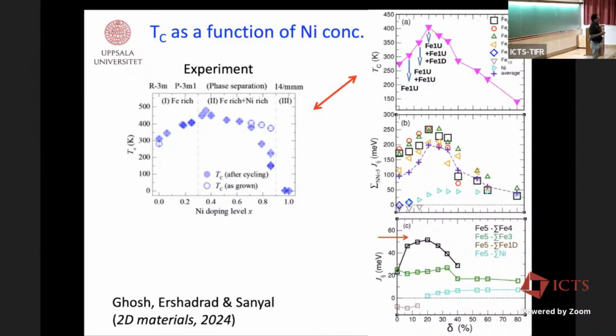So with smaller nickel doping, the TC increases, and up to a certain concentration of nickel, then it decreases. And then we wanted to find out, and in our simulation, we do not have any chemical inhomogeneity. We just have simple-minded calculations, but these are also DMFT calculations, but still we do not have the possibility of considering clustering or phase separation in our simulation.